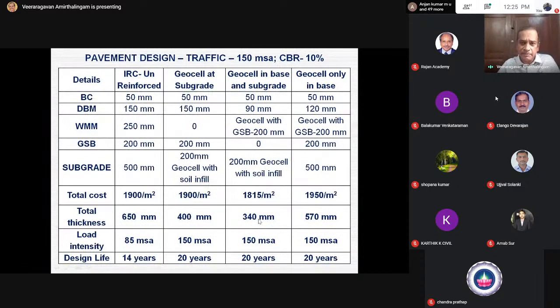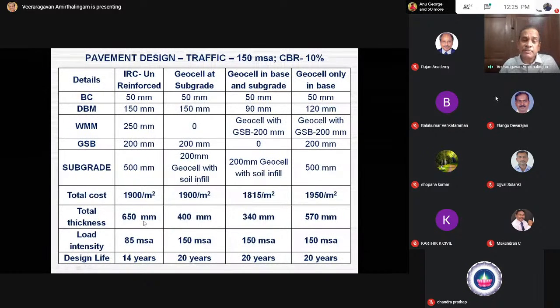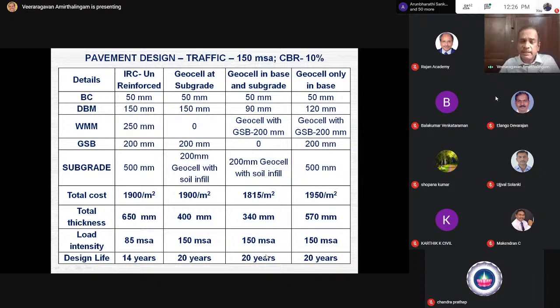Even in case of high CBR, instead of 650 millimeter pavement thickness, I can bring down the thickness from 650 to 340 using a geocell, using both in the geocell in the base and subgrade. If this lasts for 15 years, this can last for 20 years. So the future is on use of alternate materials. Instead of stabilization, I can use even a geogrid. I can improve the strength and hence guarantee you the performance. Earlier, you can ask me, why were you not adopting all these years? We were not having a code of practice all these years, so we were not adopting.